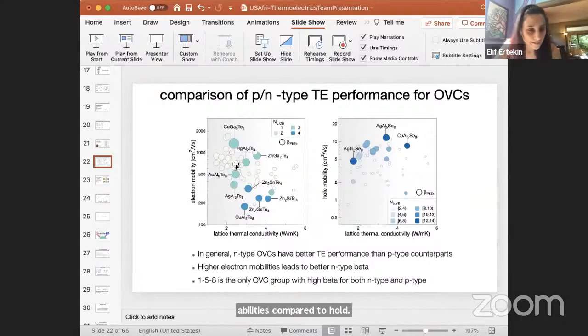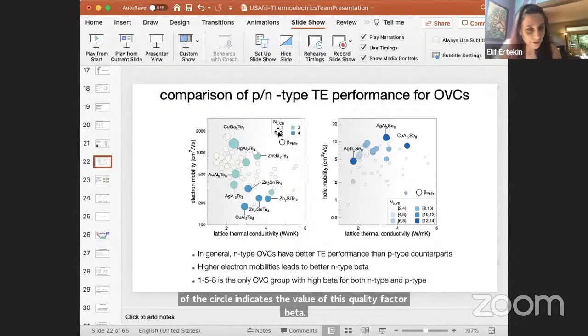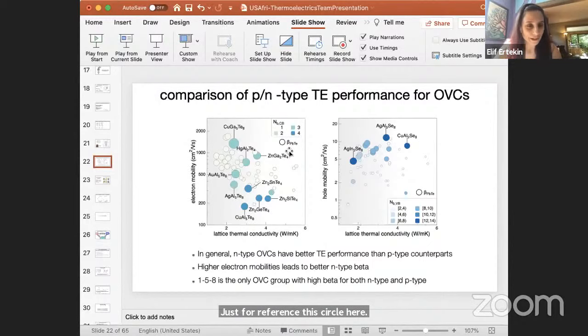And then the points on this plot are colored according to the band degeneracy for the carriers. Again, the size of the circle indicates the value of this quality factor beta. Just for reference, this circle here shows beta for lead telluride, which is a classic thermoelectric material. So any circle that is larger means that we predict that this material has the potential to show better thermoelectric performance compared to lead telluride.